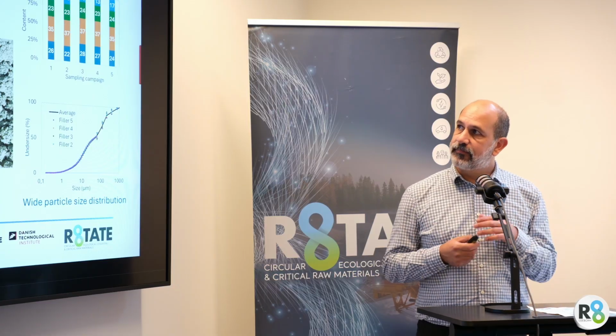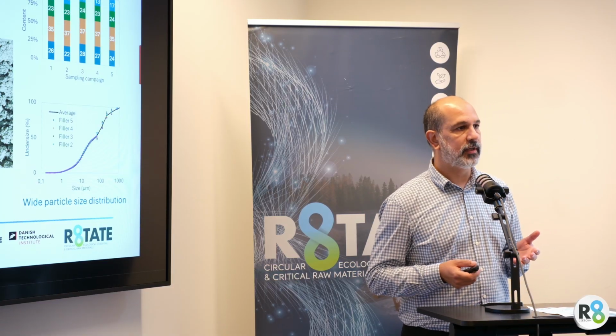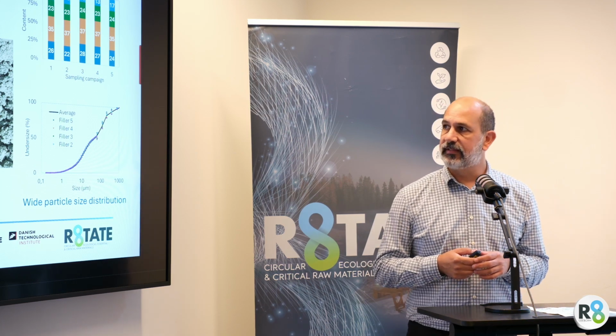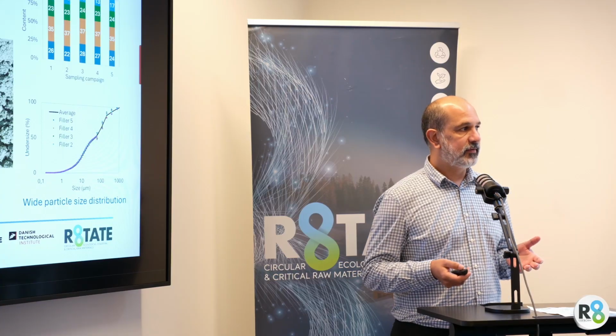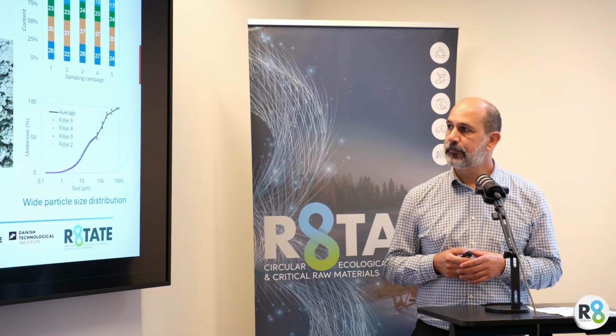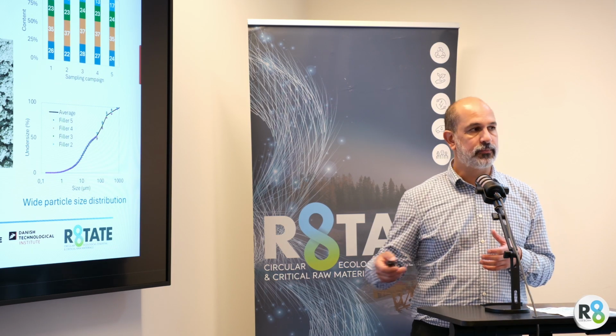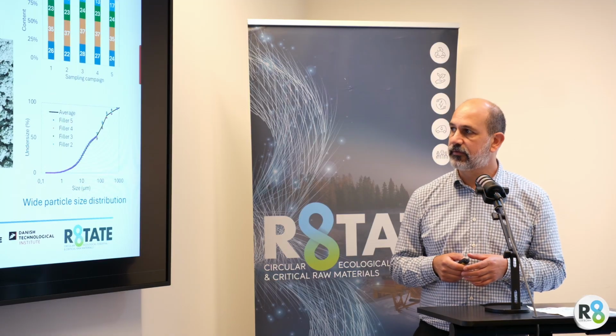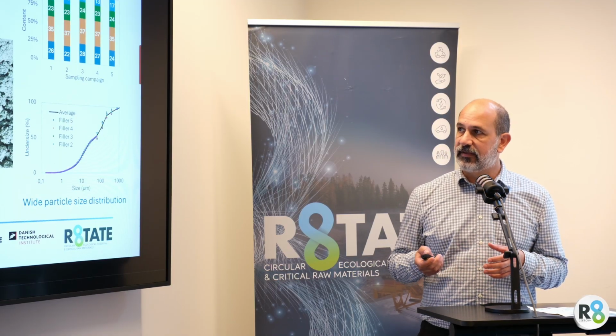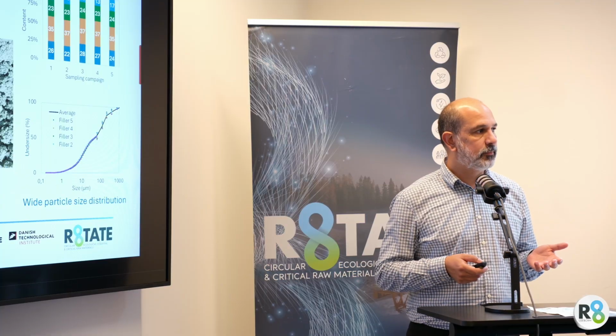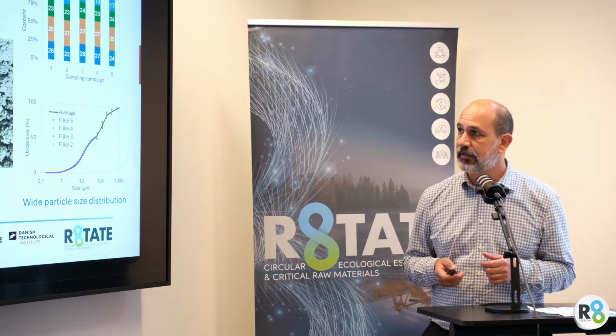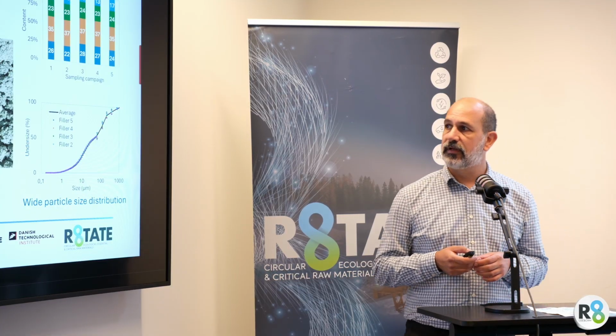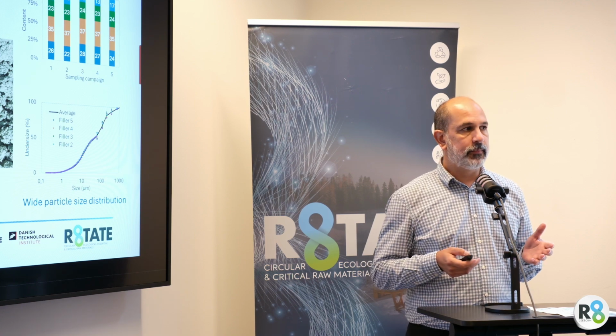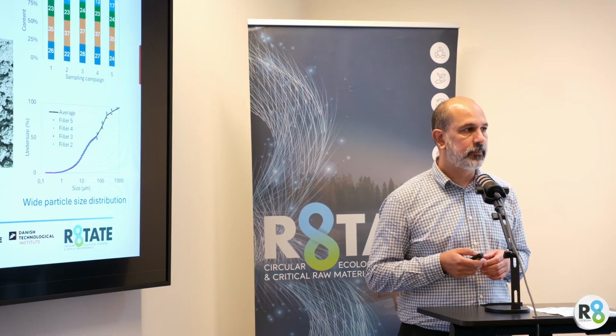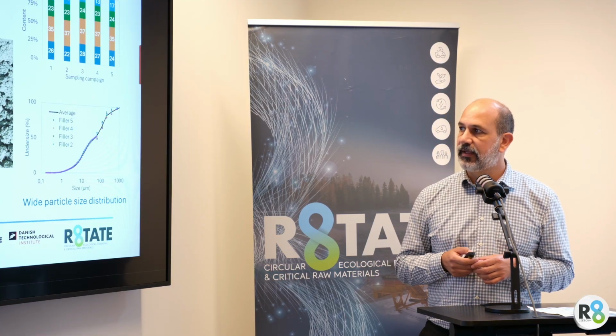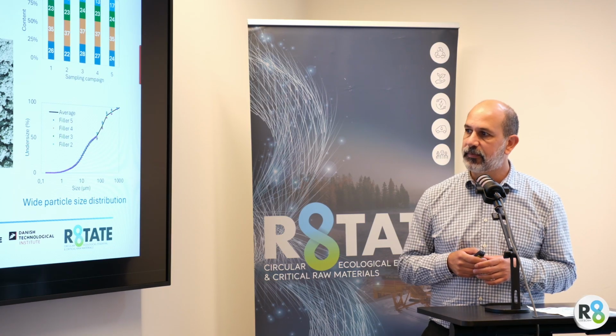So why is this valorization important? Mostly because of the volume that is processed at the production plant of Velde. They process excavated material to produce secondary aggregates mostly. But in this production, the washing process to remove the fines, which are very detrimental for the properties of the aggregates, are left as a sludge that accounts for 20 to 30% of the weight of the processed material. So that's a significant amount of residue at the rate of approximately 45,000 tons per month. And that's why a valorization path for this material is very necessary.